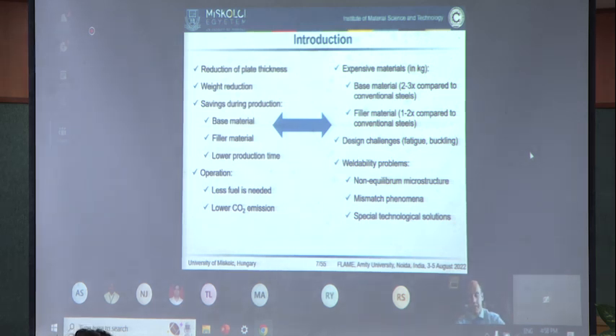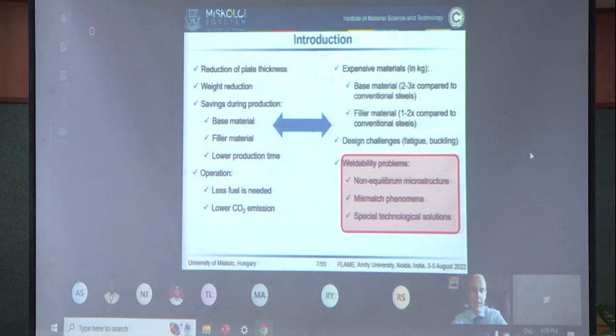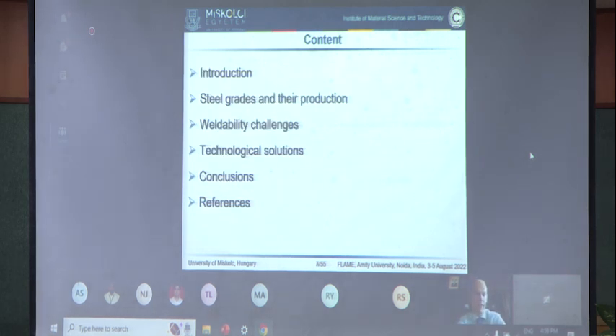Weldability is also a hot topic. Basically, these steels have a non-equilibrium microstructure, mostly martensite, bainite microstructure, and these different kinds of variations. Even sometimes some austenite content can be identified in the microstructure. The mismatch phenomenon is also a hot topic: how we can select the proper filler material for the welding. And of course, special technological solutions are needed to have at least similar strength and toughness in the joint as the base material. In my presentation, I will focus on the weldability topics, but based on this screen, you can see that it's a more complex problem.